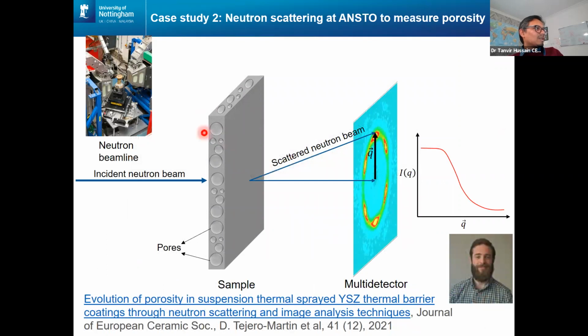That's Daniel, who's in his final year of PhD studies. All of these coatings have got porosity, and porosity is not a bad thing in all coatings. In some cases, porosities are highly desirable, because porosity allows us to have lower thermal conductivities. So Daniel was using a neutron beam at ANSTO in Australia, using neutron scattering to measure intensity over a Q vector to understand the porosity within the coating. Because of the nature of these coatings, they are in the nano range, so it's very difficult to measure the porosity using conventional techniques.